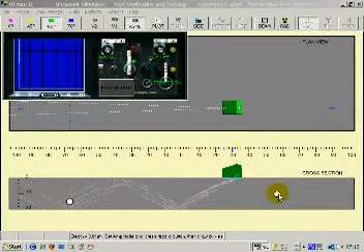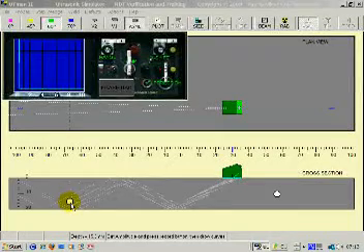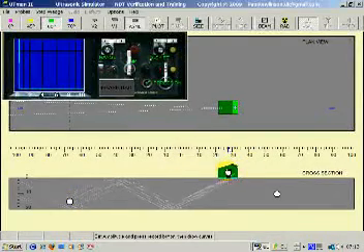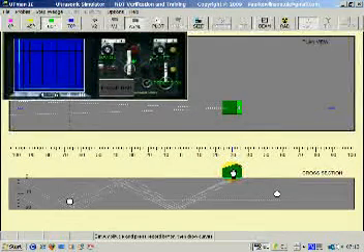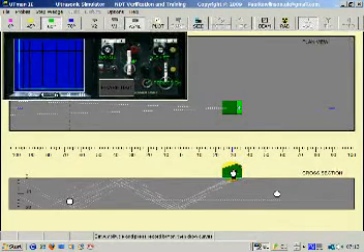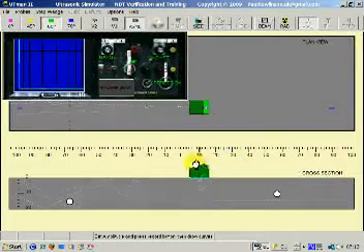An ASME block has holes drilled in it of a specified size. They're called side drilled holes. And we have to draw a DAC. Now, amplitude decreases by distance. Just like a real echo, it will diminish by distance.